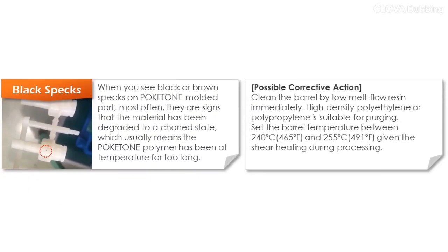When you see black or brown specks on a polyketone molded part, most often they are signs that the material has been degraded to a charred state, which usually means the polyketone polymer has been at temperature for too long. Clean the barrel with low melt flow resin immediately. High-density polyethylene or polypropylene is suitable for purging. Set the barrel temperature between 240 and 255 degrees Celsius, given the shear heating during processing.